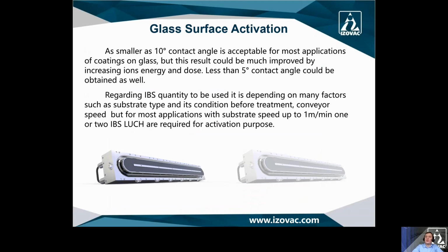A contact angle as small as 10 degrees is acceptable for most applications of coatings on glass. But this result could be much improved by increasing ion energy and dose. A contact angle of less than 5 degrees could be obtained as well. Regarding the quantity of ion beam sources to be used, it depends on many factors, such as substrate type and its condition before treatment, conveyor speed, but for most applications with substrate speed up to 1 meter per minute, 1 or 2 ion beam sources are required for activation purpose.